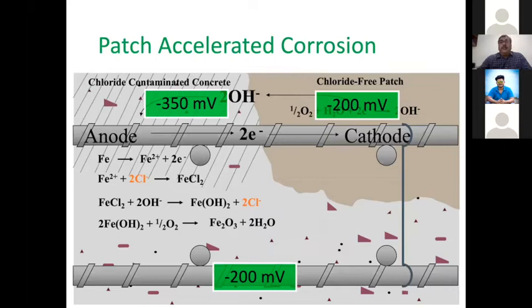Sometimes you might have a half cell potential of minus 450 or minus 350 all over the structure, and the delta is not high. Like all around you have minus 350, minus 360, minus 370. Because of less difference of half cell, you have a very low rate of corrosion and you don't see cracks. But you will see cracks even though half cell potentials are minus 300, because the delta was high. So difference of half cell potential comes into the picture.